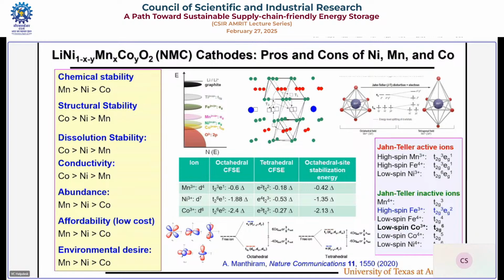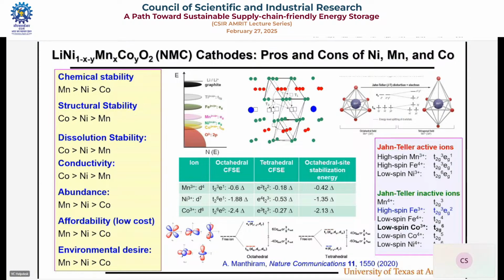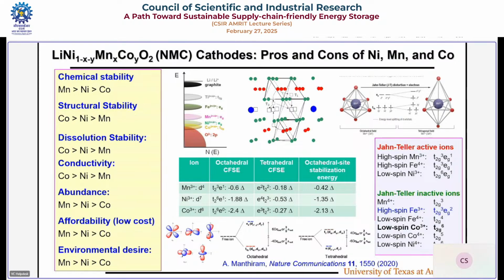This has a layered structure. This is the transition metal ion layer. This is the lithium layer. If I charge it, I remove a lot of lithium from that layer. No positive charge here. There is a negatively charged oxygen. Negatively charged oxygen. They don't like each other. So what will happen? To have charge balance, this ion will tend to go from this layer to this layer. So charge can be redistributed. When it goes, it cannot directly jump from that 6-fold octahedral coordination to this 6-fold octahedral coordination. The barrier is too huge. So the path is from that octahedral site to a neighboring tetrahedral site to this octahedral site.